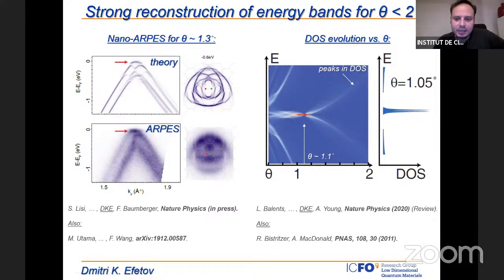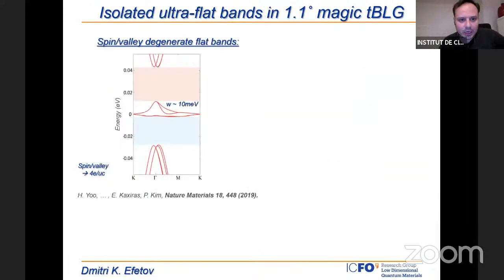So that means, in other words, the bands become extremely flat, and somewhere close to 1.1 degrees we see extremely flat bands. And these flat bands, of course, have extremely high density of states. And this high density of states in turn means that interactions can be quite strong in the system. Okay, so this is a typical band structure, which we usually use now.